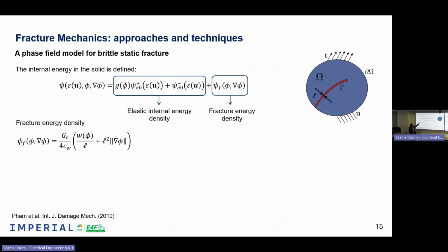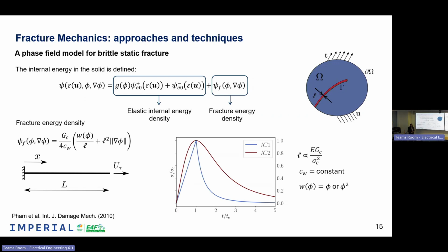So looking at this definition, this is the definition for the fracture energy density, you can see that depends on different terms. One of these terms is GC, the parameter given by Griffith, the first researcher that I told you that was investigating that. The other parameters, they can be estimated applying a one-dimensional case. So one-dimensional case is very interesting because we can get the analytical solution of this problem. No? So we represent the tensile stress with respect to the tensile strain. And you can see that we assume that when the tensile stress is arriving to a certain critical value, that is called the tensile strength, then catastrophic damage will happen, no? The crack will arrive.